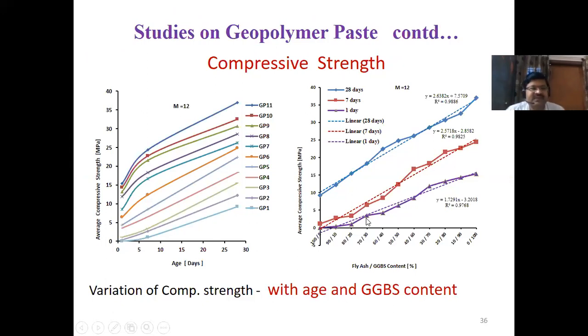If you see the left-hand curve, average on the y-axis is compressive strength, x-axis is age. So as the age increases, the strength also increases. So this is same as the cement composite. Many of the properties are similar to cementitious materials, right? Now, if you see this right-hand curve, it is compressive strength versus the fly ash GGBS content. So first one is fly ash, second one is GGBS. So if the fly ash is 100%, strength is 0, no activation. But if GGBS is 100, maximum strength. That means as the GGBS content increases, there will be strength development in case of ambient curing conditions of geopolymer, right? I'll go to next.